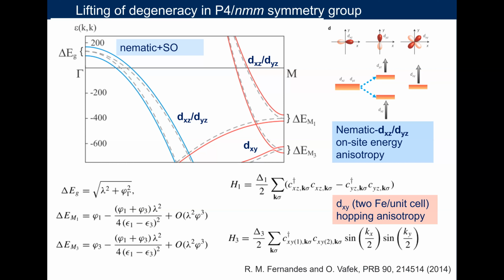Whereas if we look at the electron pockets, then the lifting of the degeneracy in this symmetry will be affected by both the nematic effects due to xz and yz, because we lift that degeneracy, but also because we develop anisotropy in the hopping terms of the dxy orbitals. And in there, this type of effects will be much more complex. By symmetry, we have two electron pockets here, and they should be degenerate in the tetragonal phase. And actually that degeneracy will be robust even against the spin-orbit coupling. It's only when we introduce the nematic effects that we should see those changing.